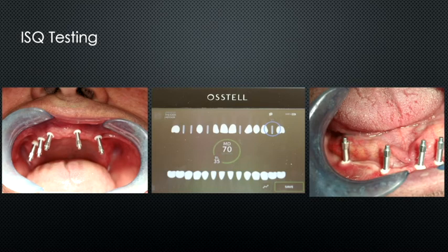What's nice with this, Xeramex has pegs where you can test the stability of the implant. So you can use the Osstell device, you put these pegs there, and with resonance frequency analysis, you can test if your implant is stable enough to be restored. With the one-piece implants, we used to do that with a Periotest, which is also a very good tool. But the RF analysis is extremely well documented to be reliable to determine how stable an implant can be before you restore it. So you look for certain values.